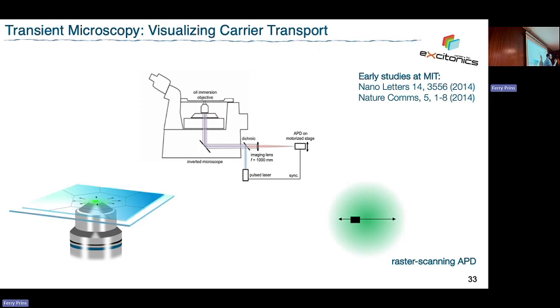And now you take an avalanche photodiode, an APD. What an APD does is it can measure lifetime. That's the time axis of our movie. But the APD, compared to the projection, the image, is actually very small. It's like a pixel within this gigantic thing. If you now put the APD on a motorized stage, then you can start taking lifetime measurements at each point. That means that you have a scanning pixel, which at the end gives you your image, and you have your time axis from your lifetime measurement.